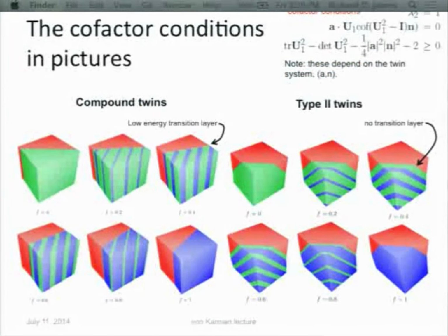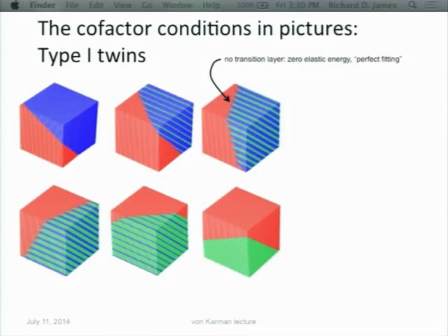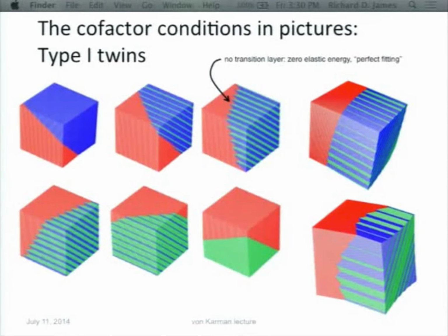There's many, many strains which are possible. And there's various cases, depending on which, you notice that this depends on the A and the N. That's the solution for the twin system. So how this looks depends on the twin system. This is the case for so-called compound twins. Turns out for type 2 twins, these conditions mean that the boundary between the bands is parallel to the interface. And there's another case, the third case, in fact, you can have interfaces in which there's no transition layer whatsoever. So in these cases, these are 0 energy microstructures, again, continuously varying. And you can also have curved interfaces with quite a few interesting things.